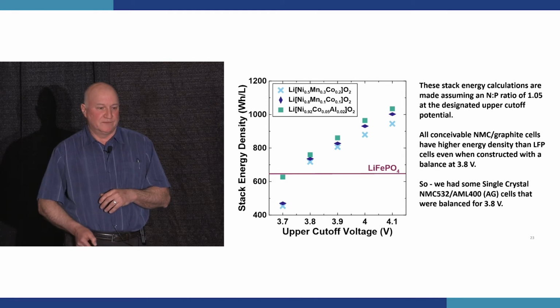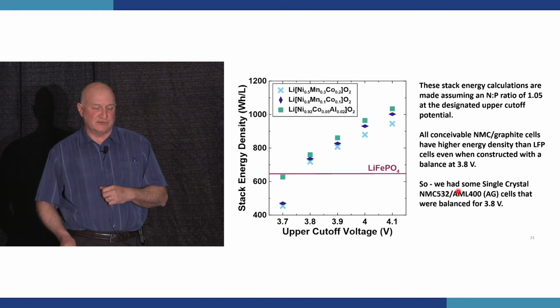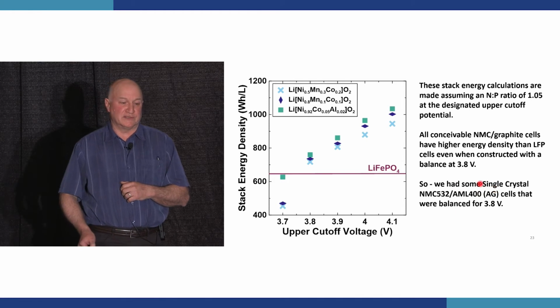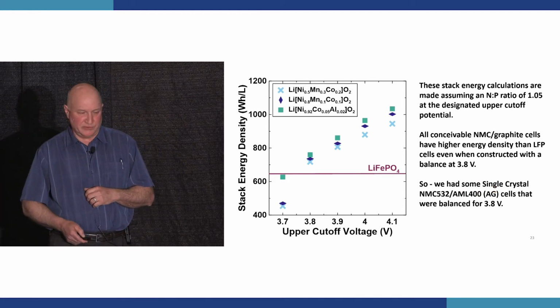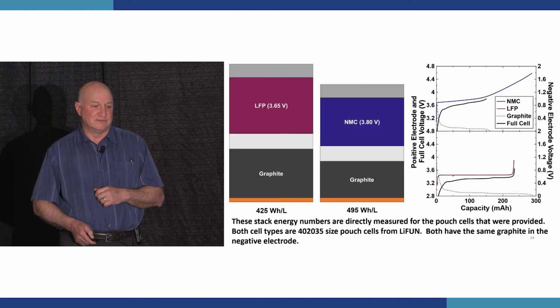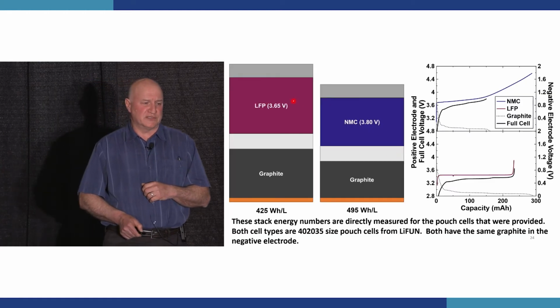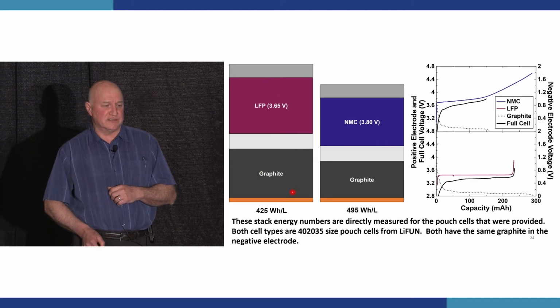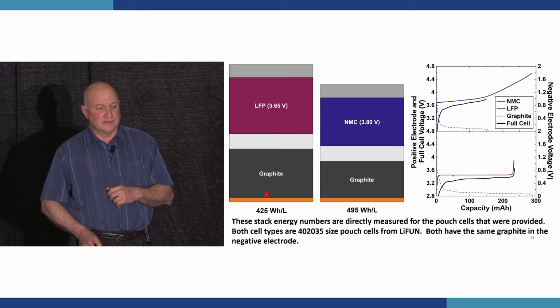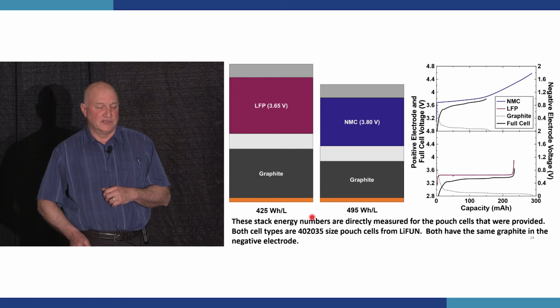So it turns out we had some single crystal NMC 532 artificial graphite cells that were balanced for 3.8 volts, and we decided to try them with this LiFSI electrolyte salt. So just to show you what the electrode stacks look like in those cells, this is the LFP graphite electrode stack, the graphite, separator, positive, just sort of a cartoon showing the relative thicknesses. This actual cell had a stack energy density of 425 watt-hours per liter, and the NMC 532 cell had an actual stack energy density of 495.